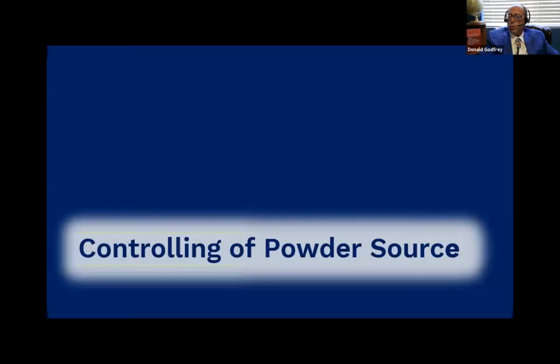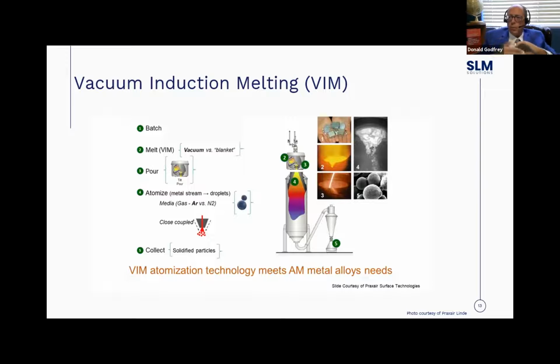All right. So how do we control the powder source? And we'll just start at the very beginning and go through to the end. When it comes to nickels or titaniums, you almost always use vacuum induction melting. And it starts with collecting the elements. When you go to the atomizer, you will see buckets of different elements, and they literally weigh those buckets individually, and they set it up by percentages. So you put the elements into the chamber, you melt them, then you pour them and you atomize them. Once it's in the melted state, they'll take high pressure argon and push it through this chamber. It comes out in an atomized state, and then we collect it. All right.